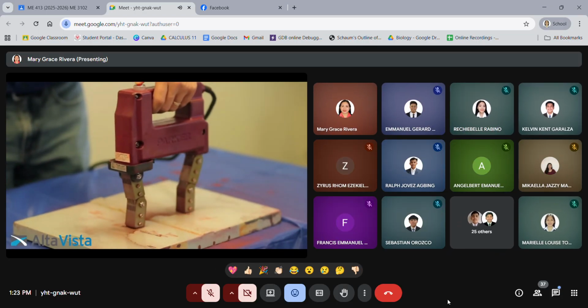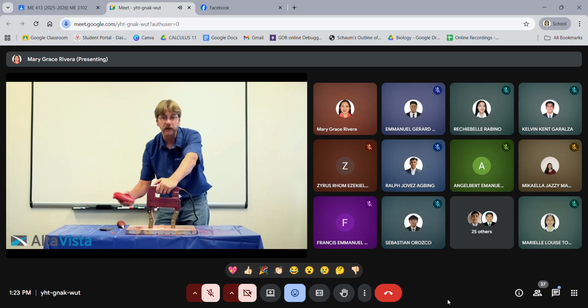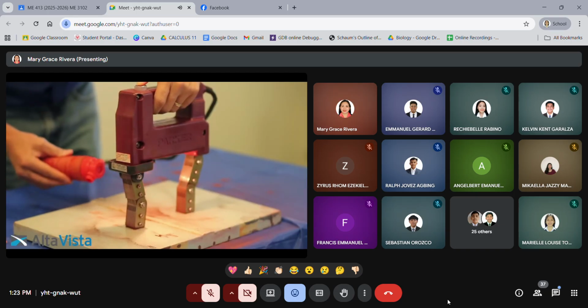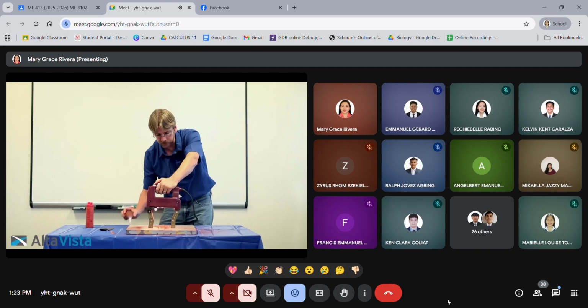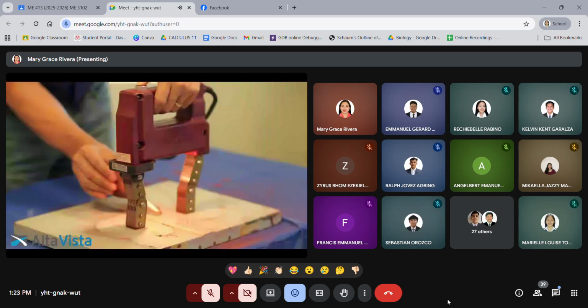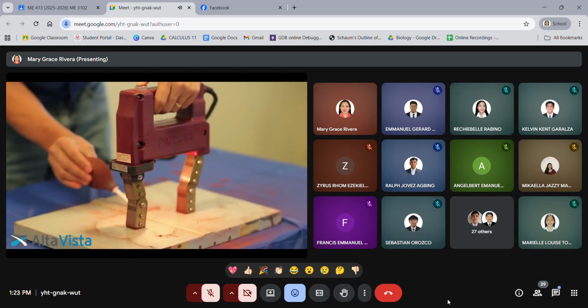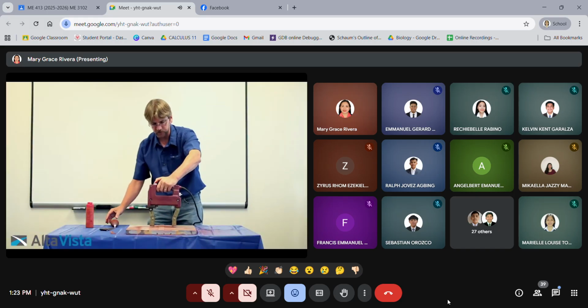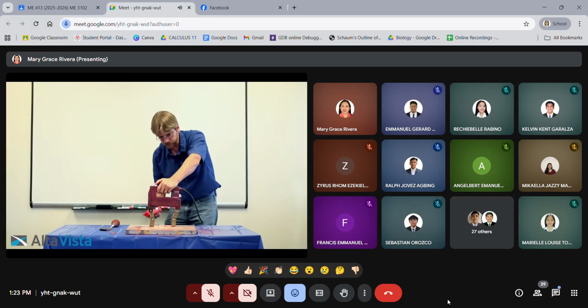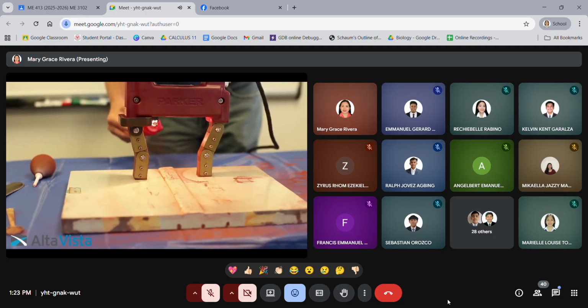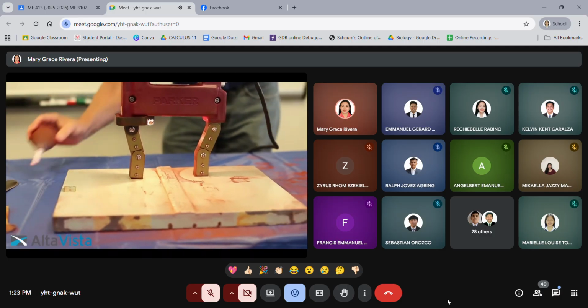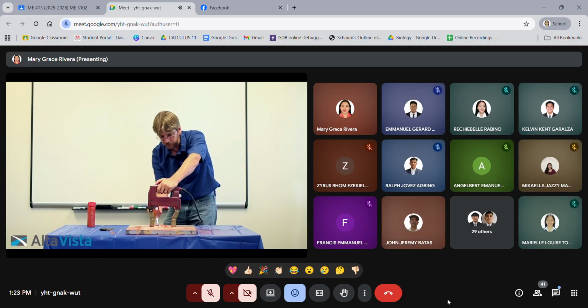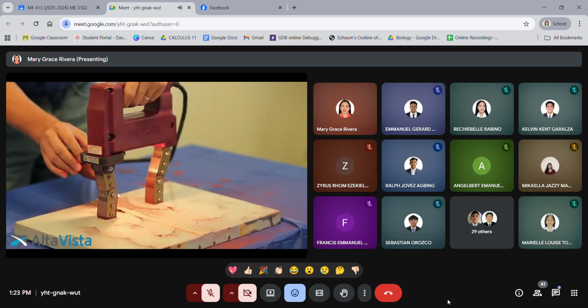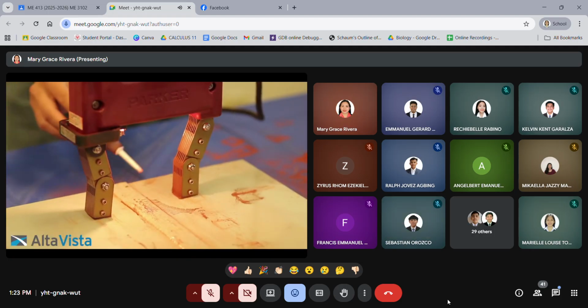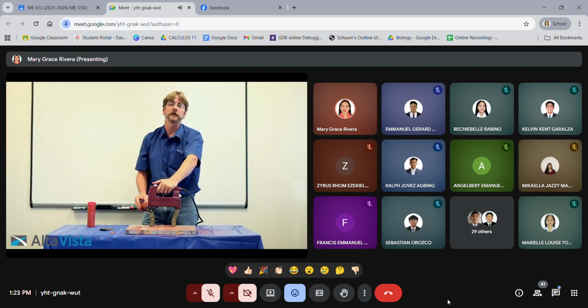So we're going to move down across the plate, making sure that we have overlap. So I make sure that I test 100% of this particular component. I don't see anything there. I'm going to move down again. And as I apply this here, we actually start to see the formation of an indication along the toe of the weld. That happens to be about a 2-inch long crack in the heat affected zone.